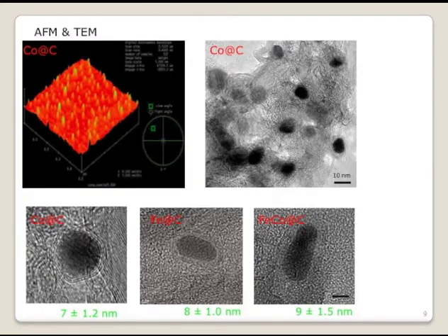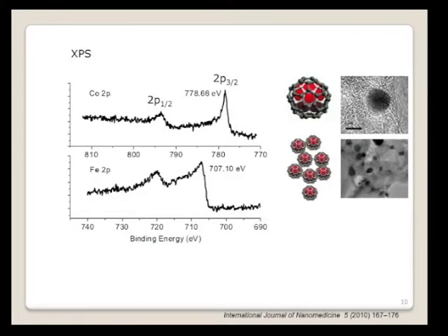How do you know this particle is in the metallic state, not oxidized during your synthesis or post-treatment? We use X-ray photoelectron spectroscopy to check the binding energy of each element, because each chemical state has its own specific binding energy. So we checked the cobalt and iron, and they match very well with the metallic state. If the cobalt is oxidized, we should see a satellite peak 5 to 6 eV above the 2p 3/2 main peak. But we didn't see it here. So it means the cobalt is well protected and in the metallic state.